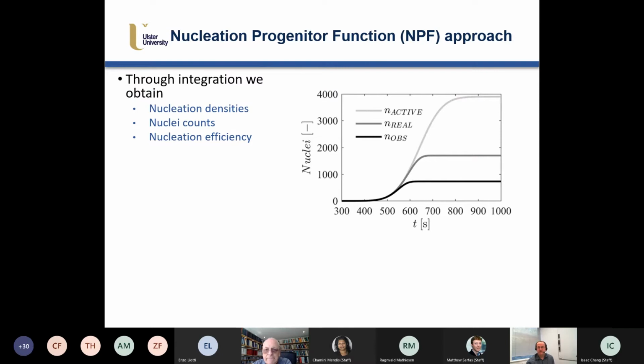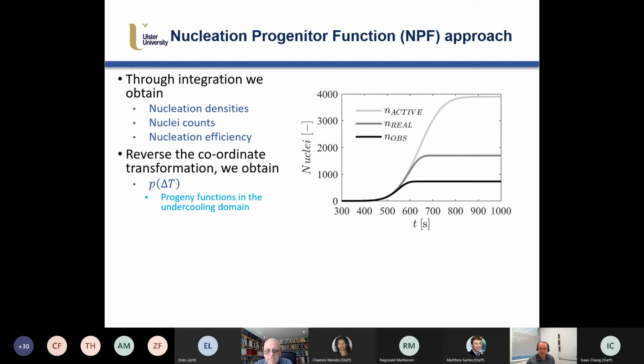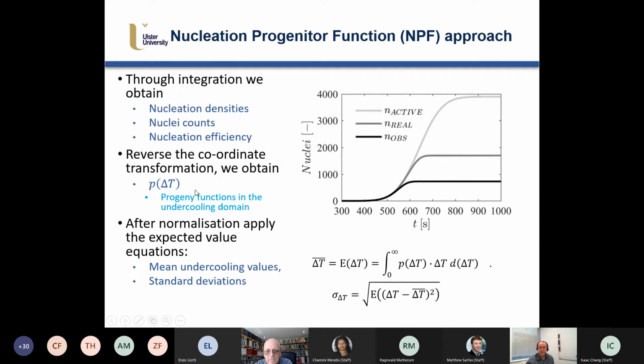And what you're able to do then is obviously integrate to get nucleation density, nucleation counts. And you can also compare the activation rate to the real rate, and you can get the nucleation efficiency. Continuing on with these statistical tools, you can reverse the coordinate transformation at any point. So you can go back into the undercooling domain, and you can normalize, which is another statistical process, and you can apply the expected value theorem. And through the application of this, you are able to determine mean undercooling, the standard deviation of the undercooling, the real undercooling. And indeed, if you wanted to, you could go higher order statistics. You could also calculate skewness, kurtosis, up to that level.